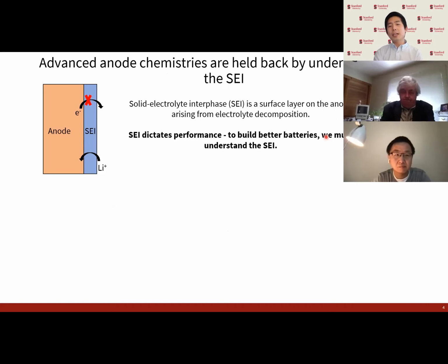But implementing this sort of high energy density battery chemistry is not trivial. This is mainly due to the lack of understanding of a structure within the battery called the solid-electrolyte interphase, or SEI. This SEI is a film that forms on the anode surface due to electrolyte reduction at the anode potentials. Now, lithium-ion batteries among electrochemical devices are fairly unique in that they operate outside of the stability window of the electrolyte. So what the SEI film does is it passivates the anode electrolyte interface to make the interface metastable.